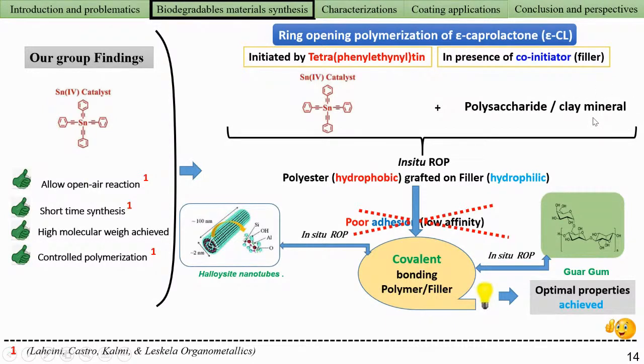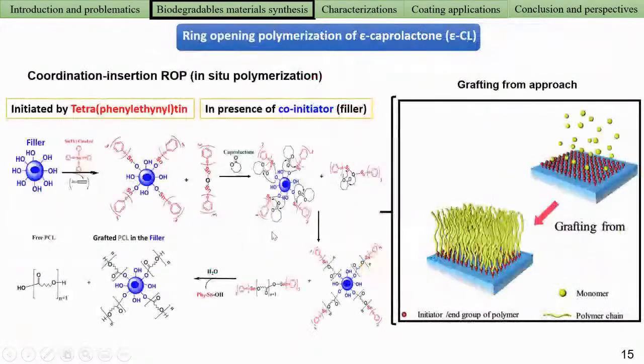As both present some OH groups on the surface, the OH groups can play the role of initiator. First we graft the catalyst on the surface, and then we start the polymerization. The reaction is easy. We mix the filler in open air with the catalyst, and we use bulk polymerization. We use the monomer as solvent too. At room temperature, we have a reaction between the fillers and the catalyst. We graft the catalyst by formation of a tin alkoxide group, and at 120 degrees we start the polymerization, and we really graft the polymer on the surface of the filler.